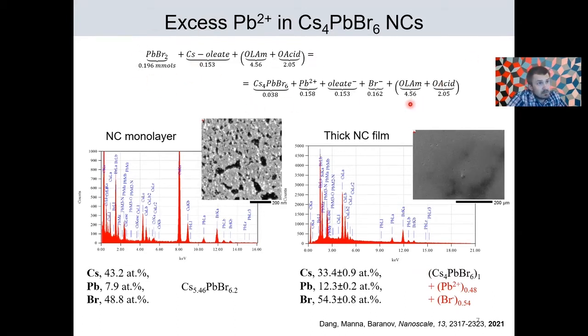So when you write down the millimoles balance and the subtractions, you figure out that as a result of this synthesis, assuming 100% yield, one should anticipate free lead and bromide present. And since we see it in the elemental analysis, it suggests that even the purification of this crystal doesn't completely get rid of lead and bromide.